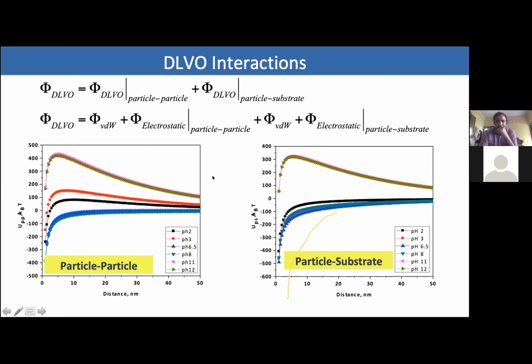and the particle-substrate system. And what you're looking at is a plot of the particle-particle interaction scaled with thermal energy for different pH ranges from 2 to 12, and again particle-substrate interactions from pH 2 to 12. What is important to notice in these plots is that there's a pH window where the overall interaction potential is negative. For example, for pH 6.5, pH 6, and pH 8, you will see that the interaction potential is negative. That means under these conditions, the particle-particle interactions are attractive.